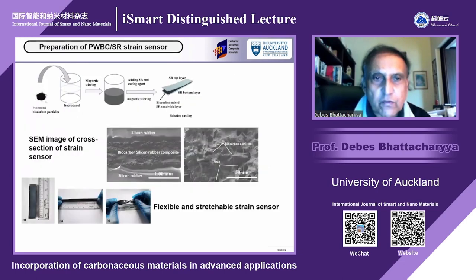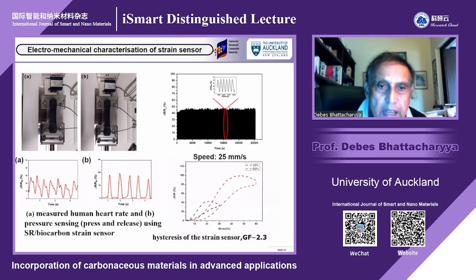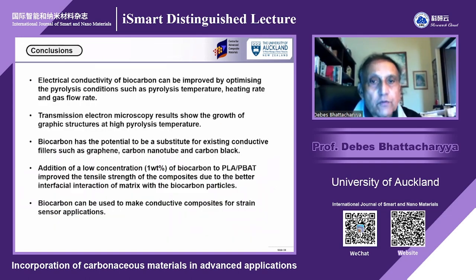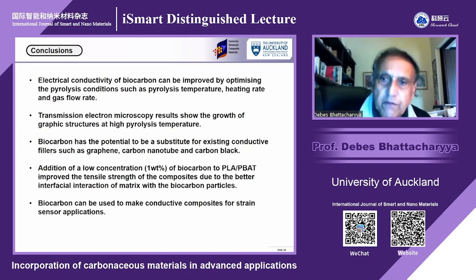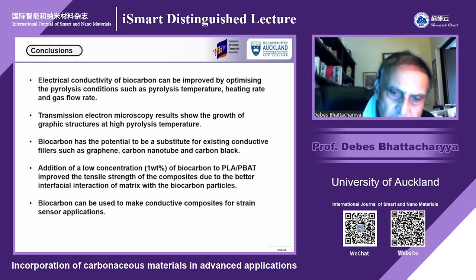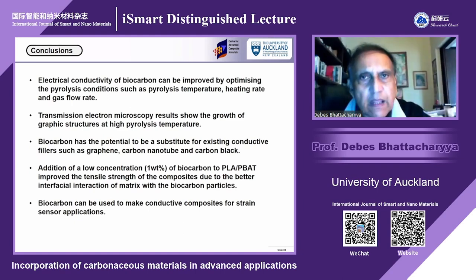And then strain sensor: we have also managed a flexible and stretchable strain sensor with silicone rubber, and that is pretty stable. In fact, we have measured human heart rate. The gauge factor is on the lower side, in my opinion, at 2.3; we should be able to improve even further. What I'm trying to say is that instead of expensive graphene material, we might be able to use commonly available biochar, made from common wood or pine wood or even coconut shell or some other nutshell, and use it instead of carbon nanotubes, platelets, or carbon black. So that is essentially what I want to say in the final part.